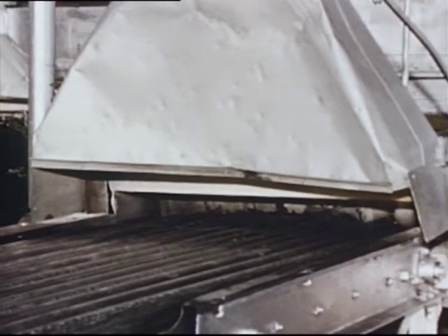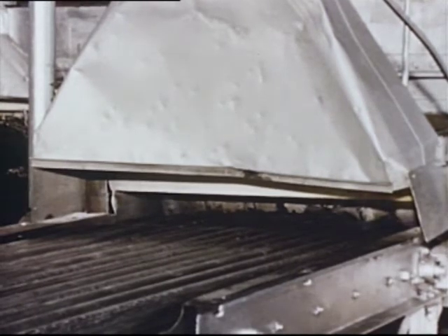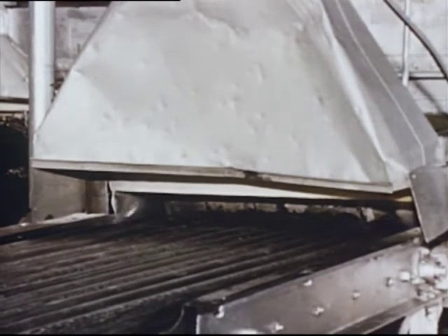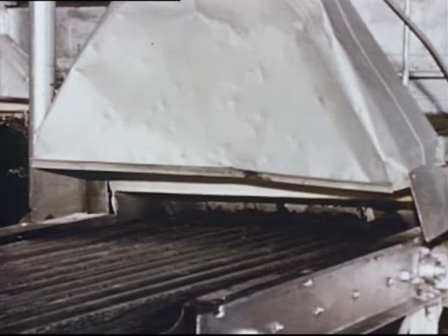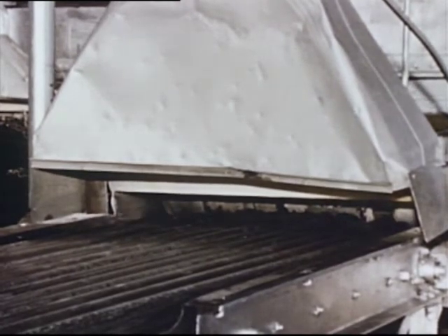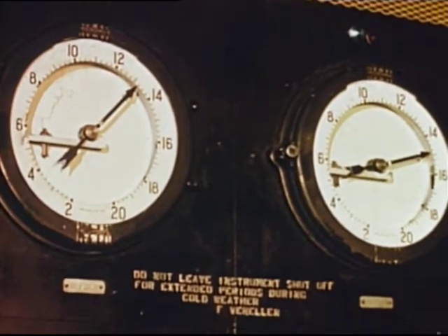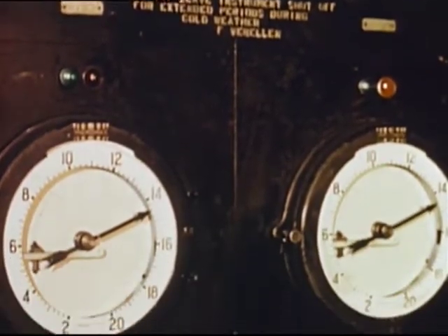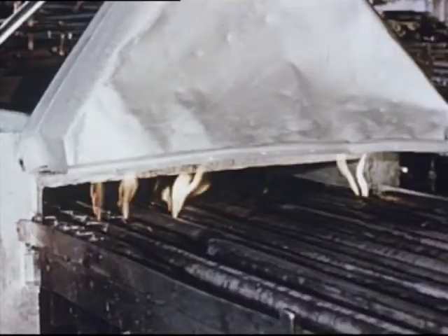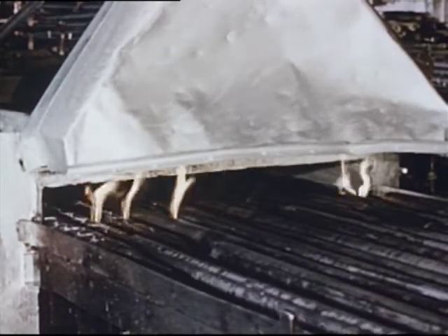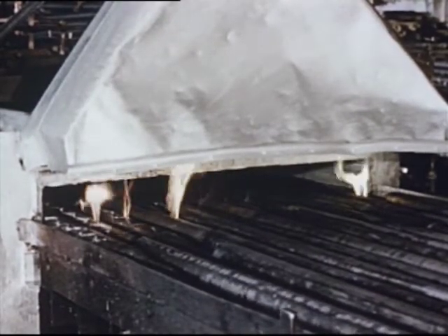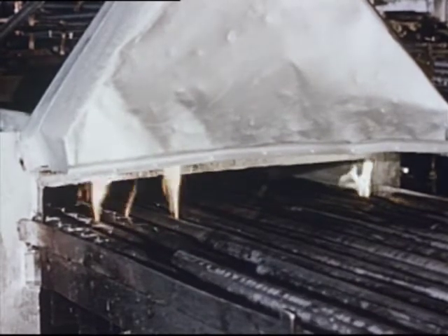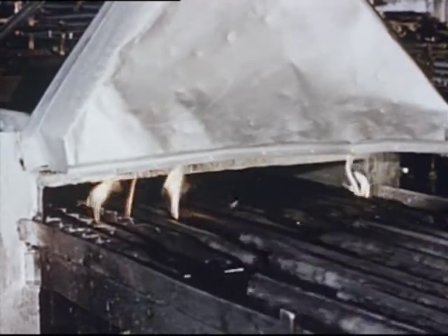Some steels can be successfully annealed in the continuous type controlled atmosphere furnaces. Tubes progress slowly through heating, soaking, normalizing, and cooling zones in carefully controlled atmospheres. Atmospheres which allow anneals without scaling and even prevent loss of surface carbon on aircraft and similar alloys. It's this precision control that greatly reduces the amount of scale usually formed during annealing, another factor contributing to high quality.